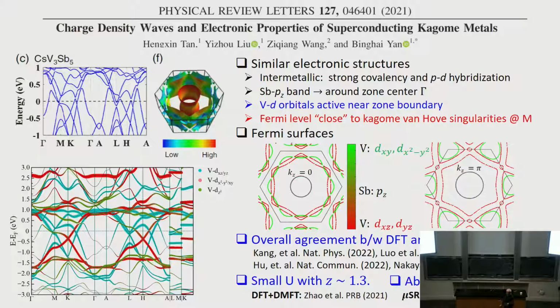You do DFT plus DMFT. That is, you want to treat strong correlation due to Hubbard-like interactions. And you find the U is not very large. Right? The mass renormalization 1.3 is weakly correlated. There is no local moment. This was also seen in muSR data. There is no local magnetic moment or fluctuations. So pretty boring.